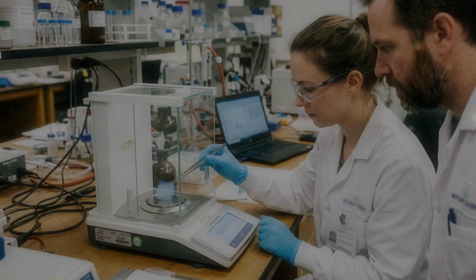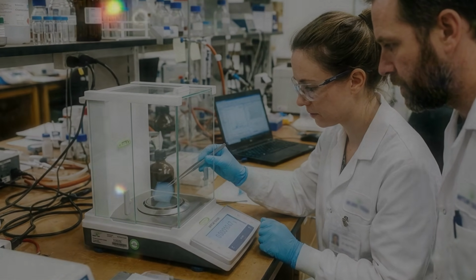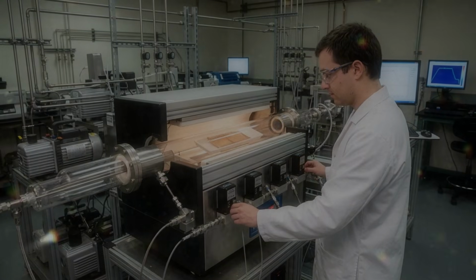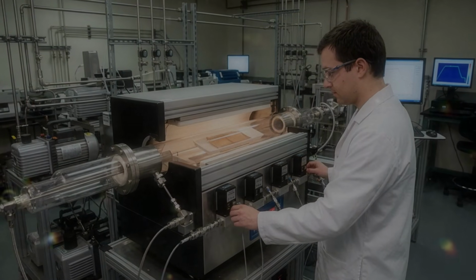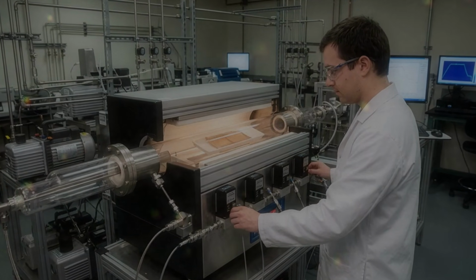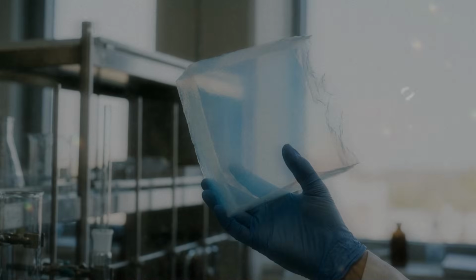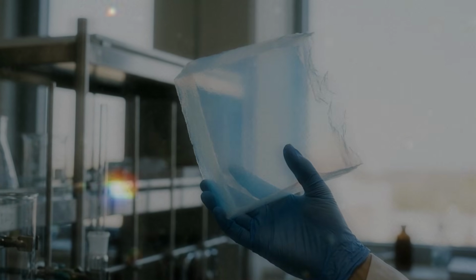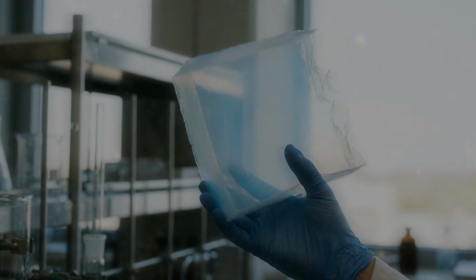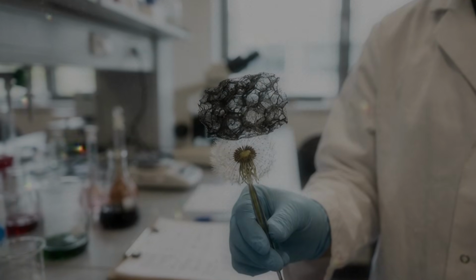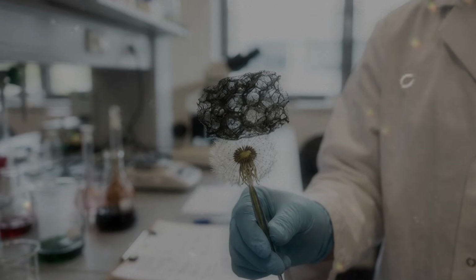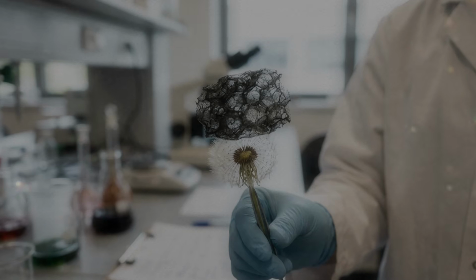Freeze drying is common because it is relatively accessible, and because the ice crystals can help create an open cellular structure. The hydrogel is frozen, sometimes rapidly and sometimes in a controlled direction. The ice is then removed under low pressure. What remains is a very light carbon framework.